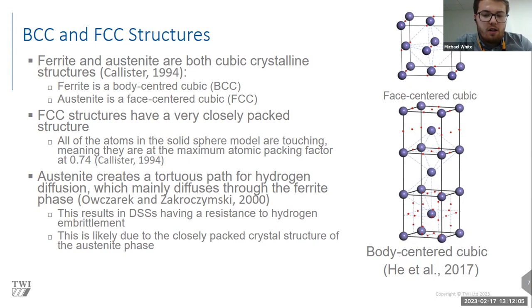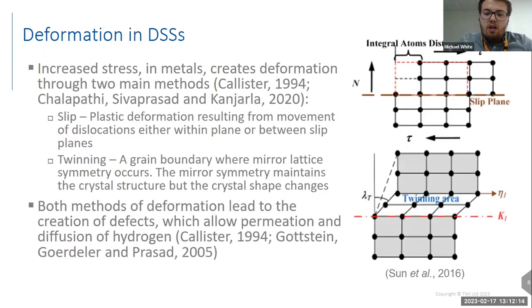However, this resistance to hydrogen transport can be altered by deformation of the duplex stainless steel crystal structure. Increased stress results in the two methods of deformation shown in the right-hand image, slip and twinning. Any form of deformation changes the crystal structure and can result in voids and defects becoming present for hydrogen to diffuse through via vacancy diffusion, decreasing the resistance to hydrogen embrittlement.